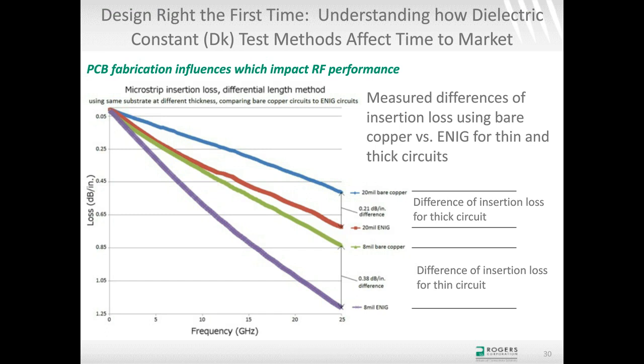And then same material, same everything, same design, except now thinner, maintaining 50 ohms as well. The 8 mil thick substrate and the circuits from that, you can see the green curve are the 8 mil thick circuits with bare copper, and the purple curve at the bottom are the same thing, 8 mil thick circuits, but now it's using e-neg. And the difference in the insertion loss there at 25 gigahertz is 0.38 dB per inch. So this shows that a thinner circuit is more affected by conductor effects, and in this case, the conductor effect is a more lossy conductor due to the nickel than copper.